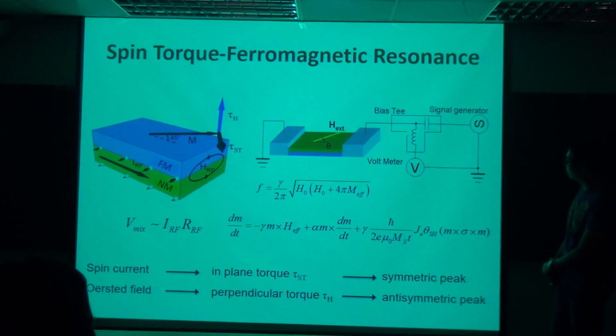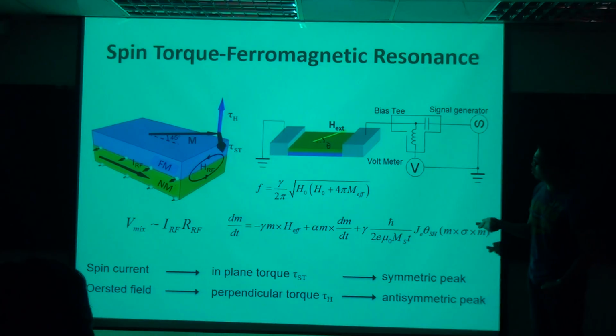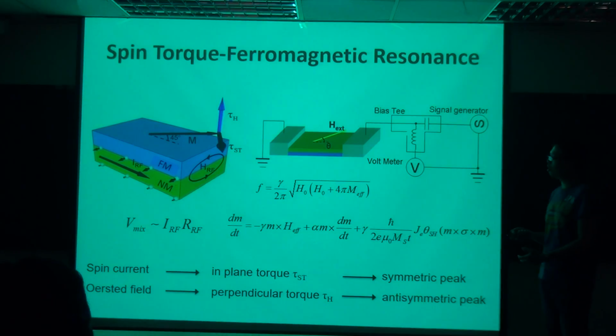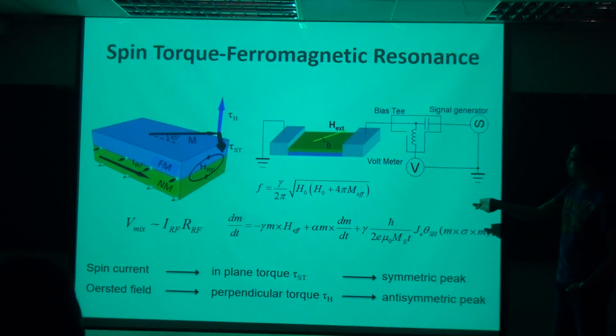At that time, in 2011, this was still a very new method, and also a very fast method, which allows you to determine the spin Hall effect very quickly. And the device itself is very simple. All you need is a bilayer structure. You just need a normal metal layer, which is the spin Hall material that you want to study, and on top of it is the ferromagnetic material, for instance permalloy, which is a soft magnetic material that people typically use. And if you send an RF current into this device, then you start to get FMR, ferromagnetic resonance, or oscillation of the magnetization.